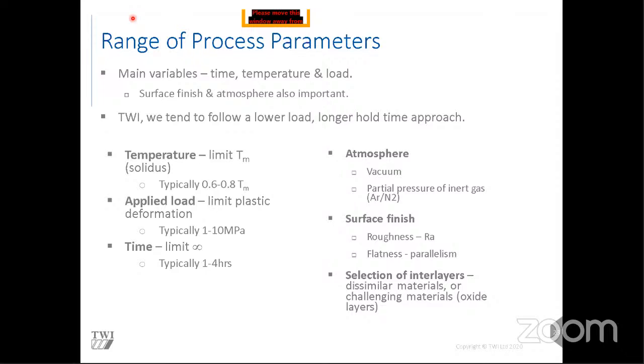The applied load is typically 1 to 10 megapascals. In certain applications where you have intricate internal features, you want to limit plastic deformation of those, so you're trying to balance pressure versus functionality. The time could go to infinity, but typically diffusion bonds take 1 to 4 hours in our furnace.